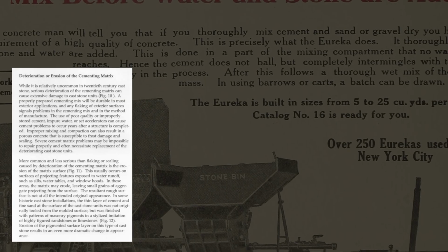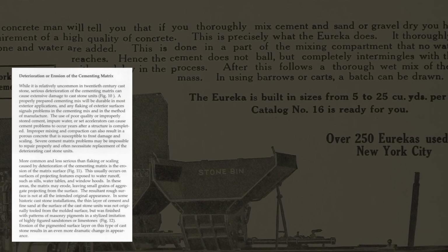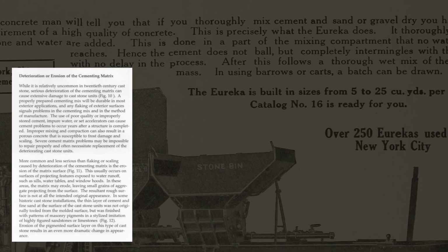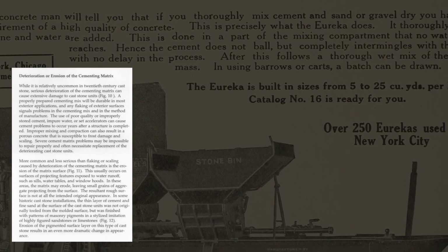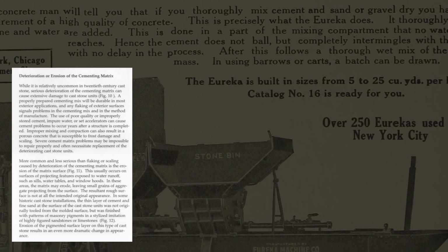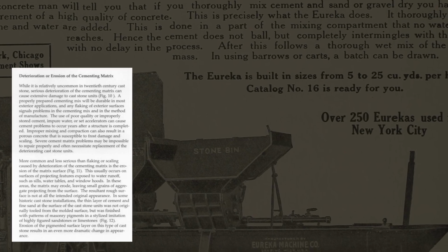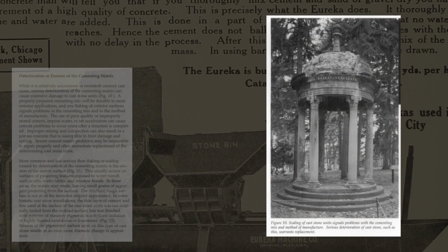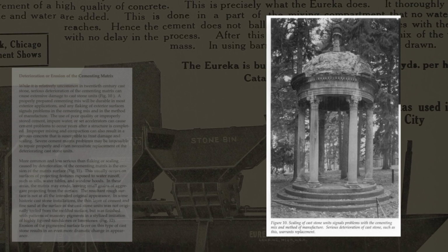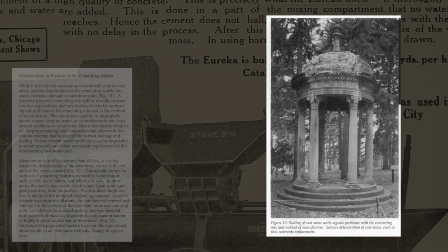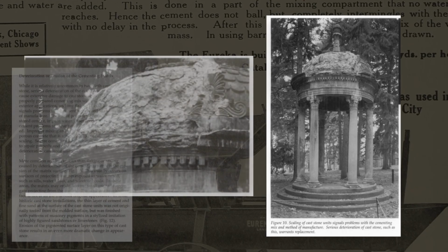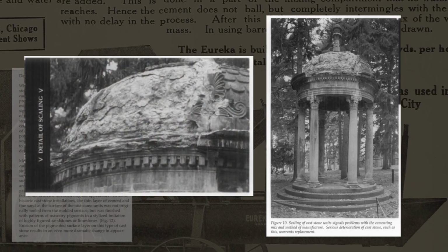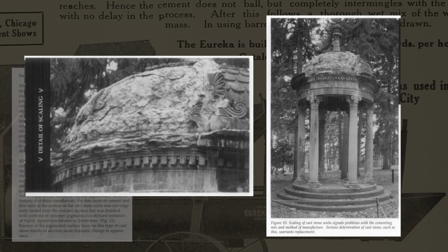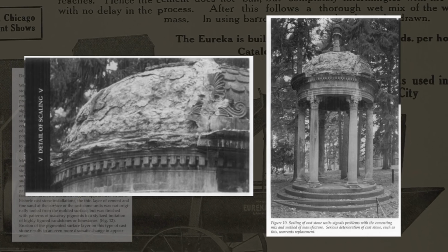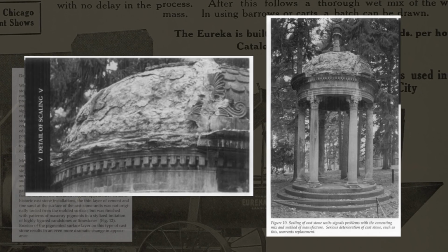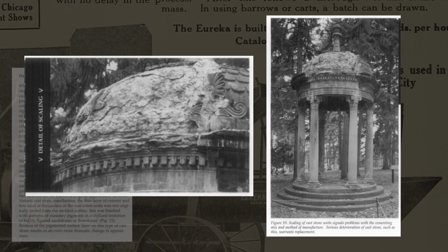Deterioration or erosion of the cementing matrix. While it is relatively uncommon in 20th century cast stone, serious deterioration of the cementing matrix can cause extensive damage to cast stone units. So here we have figure 10 showing this, and it reads as follows. Scaling of cast stone units signals problems with the cementing mix and method of manufacture. Serious deterioration of cast stone, such as this, warrants replacement. So we have a couple images here, one shown more in context and then a close-up of the deterioration.